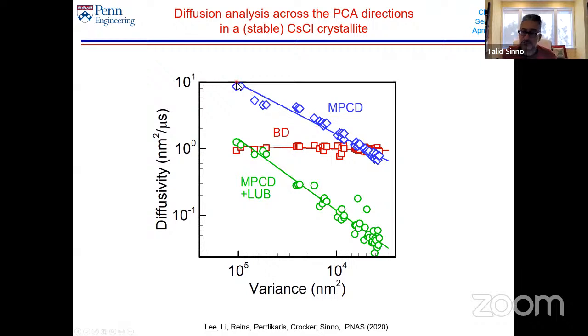And in fact, what's interesting is that they're actually higher than the Brownian dynamics diffusivities. That's because fluid mechanics actually assists correlations, and that allows things to slide over each other more easily because the motions are correlated. When you add lubrication, that starts creating shear friction, and that lowers all the diffusivities. But the important point is I now have a very wide range of diffusivities along different eigenvectors. Long story short, the high diffusivities correspond to FCC generating outcomes, and the low diffusivities correspond to HCP generating outcomes. This is how fluid mechanics biases the outcomes of these transformations.